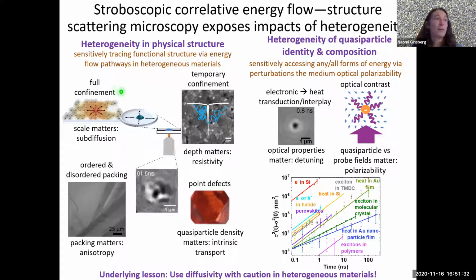So for example, full confinement, or temporary confinement, or much smaller scale atomic defects, or even just the molecular scale packing in molecular crystals. And in all of these cases, we were able to learn about different phenomena that are very different than what one might expect in bulk, and to leverage different aspects of our technique. So we learned that it really matters what scale you're measuring on when you look at subdiffusive heat transport. We took advantage of depth dependence and learned about resistivity.